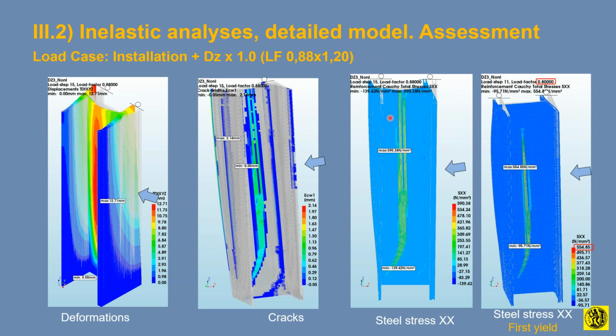So if we move back this load case and we go to 80% installation plus out of plane, this is the onset of yielding in this area here. So this shows what really happened. I mean, at 80% of the differential plus installation, yielding starts in this area here. This is the first onset of yield of this specific caisson.